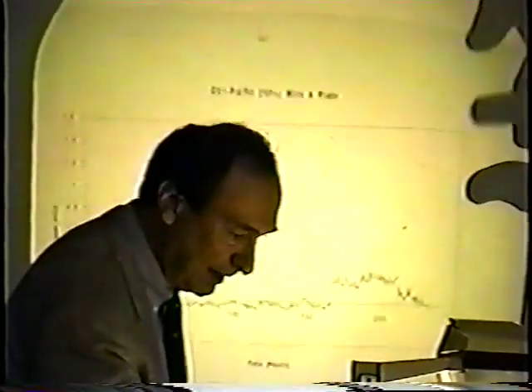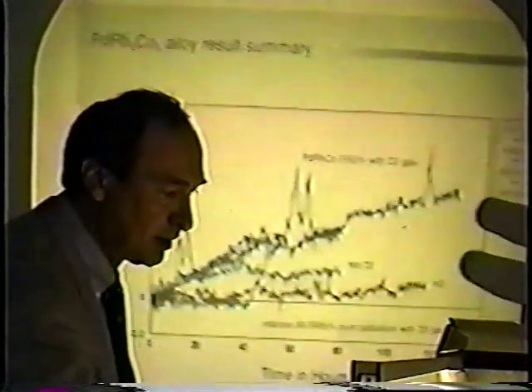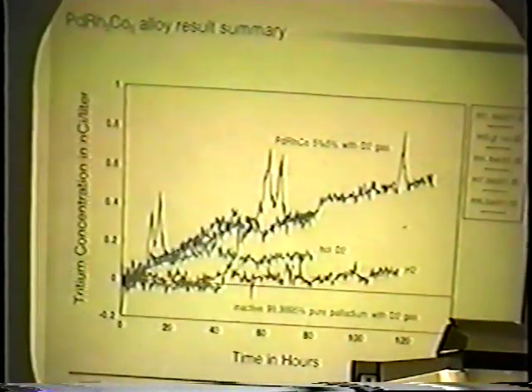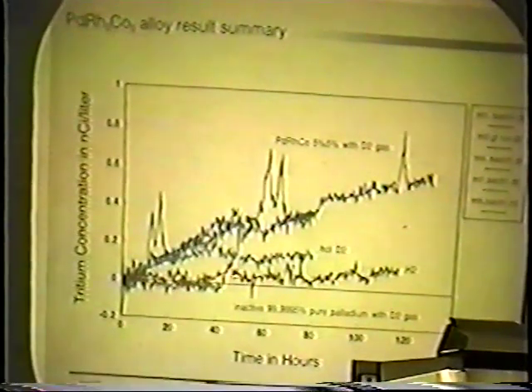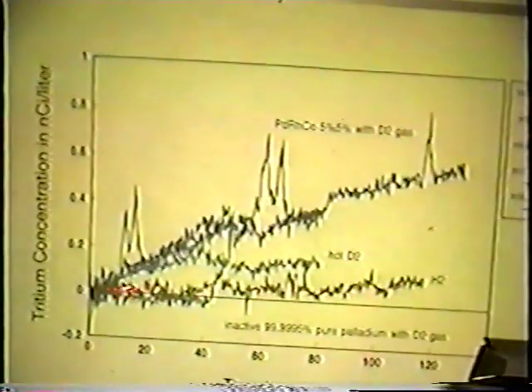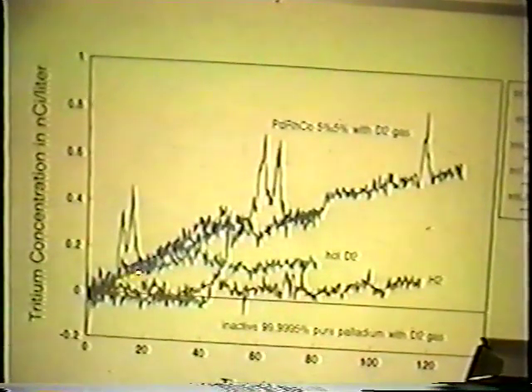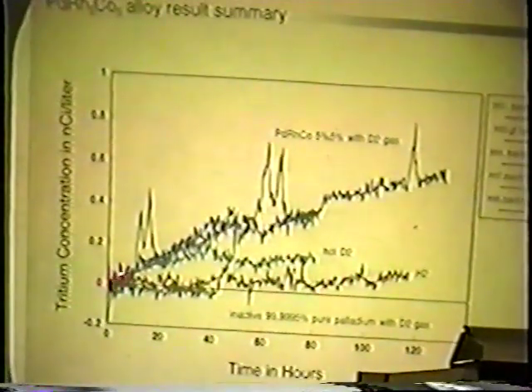Well, this is at 10%, and so we tried lower alloys, and I'm going to skip about 6 months worth of work back here. And so what we came up with was palladium, rhodium, cobalt, which we have 5% rhodium and 5% cobalt. And here's some background runs. This again is hydrogen with this particular material. This is hot D2, where we've initially started with a low current, and then later in its life we've raised the current so that the material is dehydrogenating.